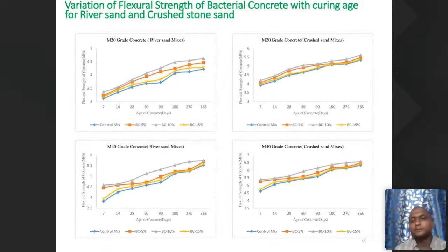Likewise, the flexural strength. We performed the flexural strength test in the UTM, the Universal Testing Machine. We cast a beam of size 10 cm by 10 cm by 50 cm, that is 100 mm by 100 mm by 500 mm. For the cube strength, we cast cubes of 150 by 150 by 150 mm, and the cylinder is 150 mm in diameter and 300 mm in height. We cast the same and dismantled them, and kept them for curing at different stages from 7 days to 365 days.